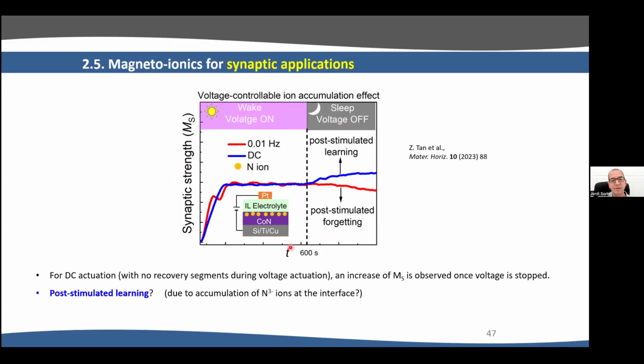This part, up to 600 seconds, where the voltage is applied, we have this increase on magnetization, nothing new. But what is a bit surprising and strange is that when we stop the voltage, in the case of the red curve, it relaxes like before. But when we apply this DC voltage, in this case, thin films, we have a post-stimulated learning. It is as if the memory gets consolidated and even enhanced without any stimuli. And this mimics a bit what happens in our brain when we go to bed, when we sleep.